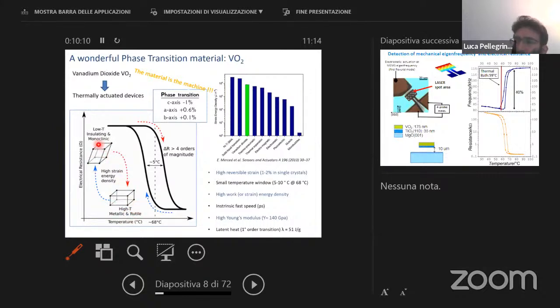So this change of crystalline structure has a lot of energy inside. It's a reversible strain, which is about 1% along the C-axis, and negative, so you have a contraction, and a positive in the AB axis of the cell. In the small temperature window, you have a lot of strain energy density. So if you see this graph from this reference, you see this is a logarithmic scale.